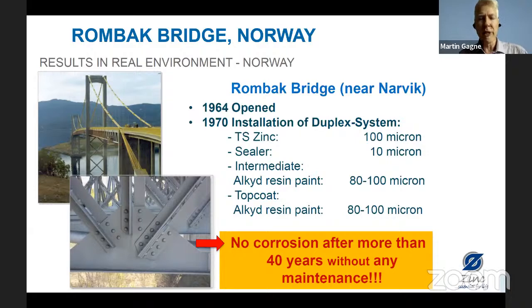So then we did a field application of the thermal spray zinc and paint. This was a pure zinc coating, 100 micron thick with a sealer. Graham had talked about not applying alkyd paints to zinc, but almost all the bridges in Norway from 1965 through to 2008, I think, when they changed, were alkyd paints. There was an intermediate coat and then a top coat.